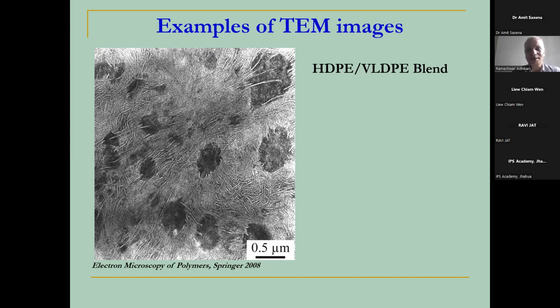Therefore, the staining agent, which is ruthenium tetroxide, is there, and that increases the density of the section. Therefore, the darker areas are the ruthenium tetroxide rich areas. They scatter more electrons and appear dark in the transmission electron micrograph. In contrast, the brighter areas should be high density polyethylene. If you look carefully, you will see that these brighter areas also constitute some much brighter areas and some less bright areas.